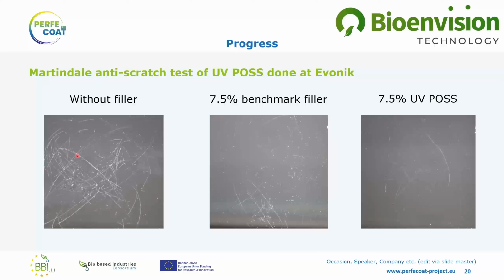In the first one, you see there's a lot of scratches in the coating after the test is done, and there's less scratches in the benchmark filler, and even less scratches in the UV POSS coating, which shows that there's an improved effect of mechanical strength of the coating due to the UV POSS as compared to the other two.